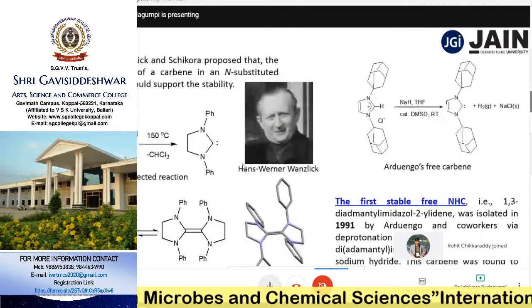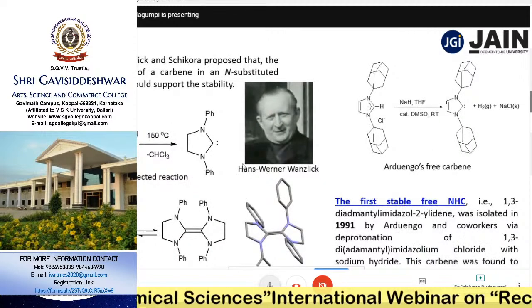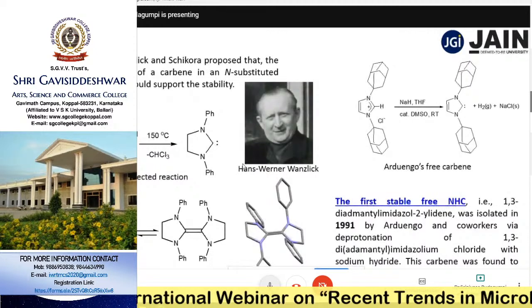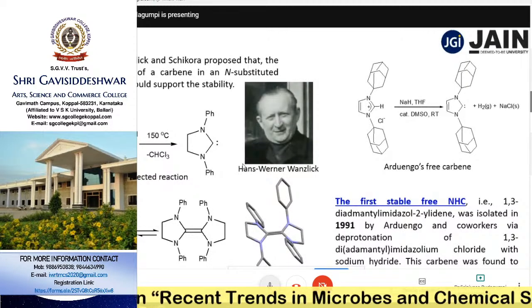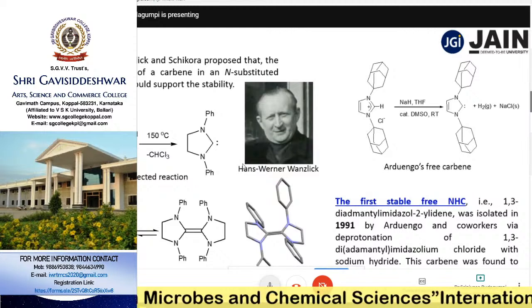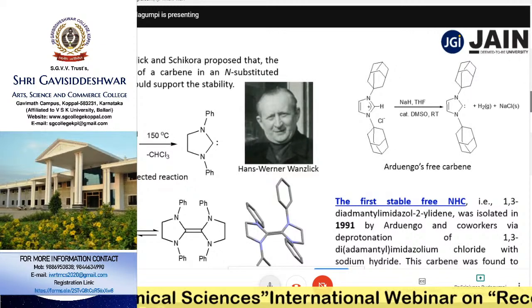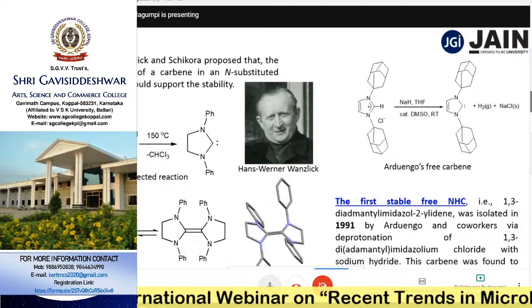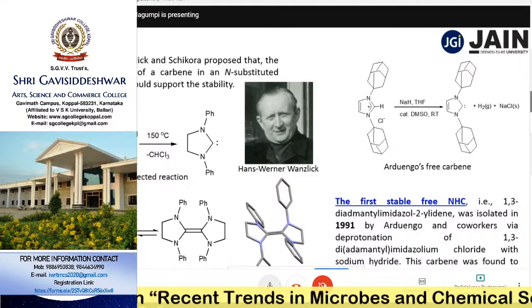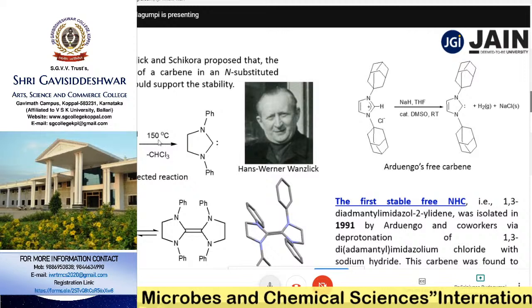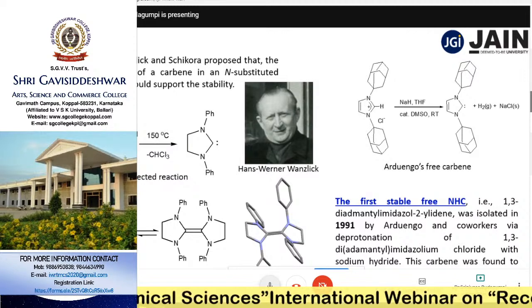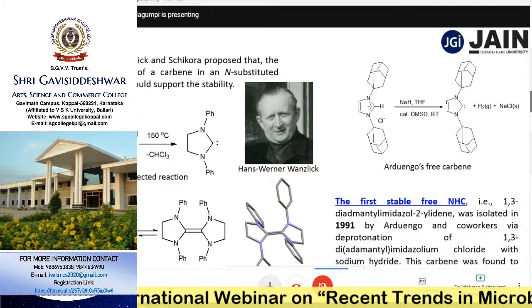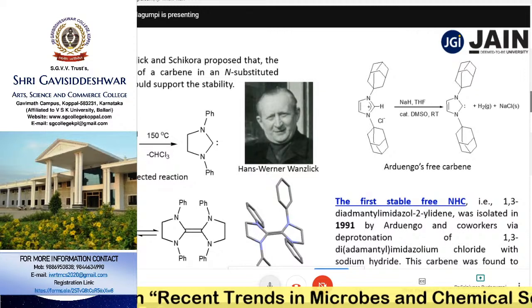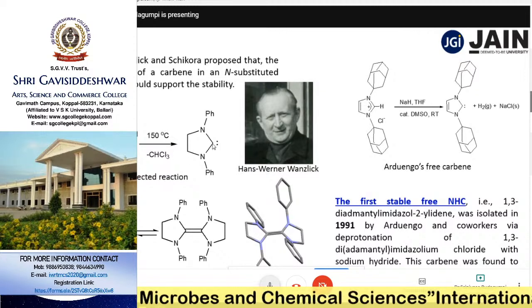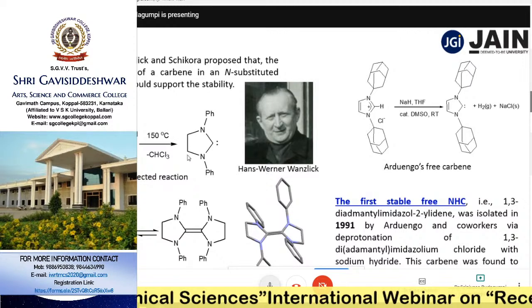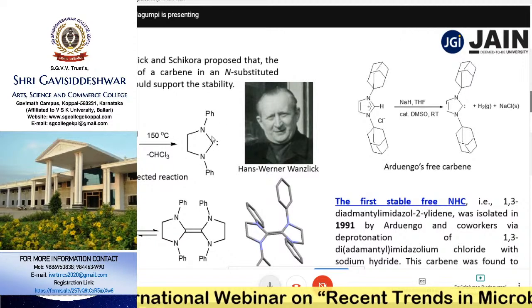Now, in the 1960s, Wanzlick and Schikora were the first people, around 60 years ago, who worked on the isolation of the free carbene. So this is an imidazolidine derivative, which has a trichloromethyl substitution at the second position of the azolium system. They thought that if they heated this molecule at 150 degrees Celsius, the H and the trichloromethyl substituent would come out in the form of chloroform, and that generates a carbene at the C2 carbon atom, numbering 1, 2, 3, 4, and 5. So a carbene was generated at the second position.